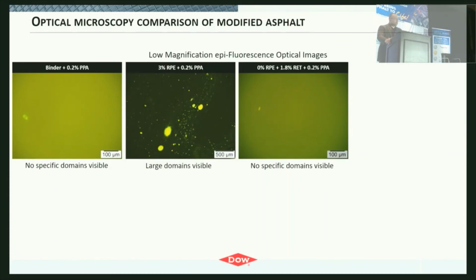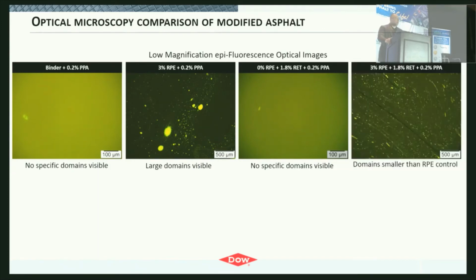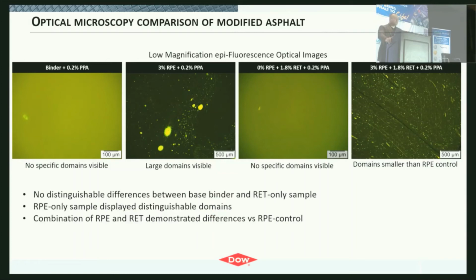This is 3% of the recycled polyethylene, and you start seeing domains that are large and visible. If you look at the dark field portion, you can see there's a very high level of contrast. And so the plastic is fluorescing very highly here. And then if you add the RET, you can see that the domains become much, much smaller. And so really there's no distinguishable difference between the RET only, the unmodified, and we did seem to improve the micro domains of material here. And typically, 3% plastic is going to be on the very high side. Since we're trying to meet PG spec, that would be typically dosed down to lower levels.